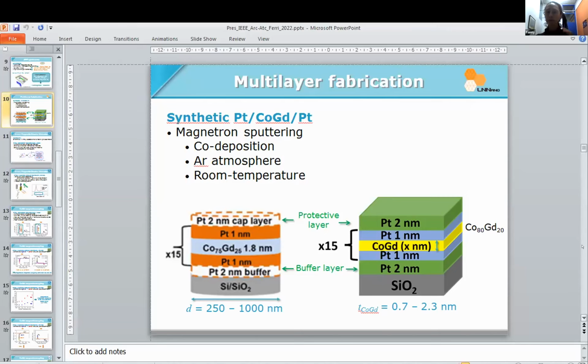The difference is, in one we did some lateral confinement, so it was nanodiscs, where we varied the diameter between 250 and 1000 nanometers. In this case, the cobalt gadolinium alloy was 75 and 25, and the thickness was pretty thick, actually 1.8 nanometers. In the other, we changed the composition of the alloy a little, but it actually doesn't change so much about the properties. But here what we varied was the thickness of the cobalt gadolinium, between 0.7 nanometer and 2.3 nanometers.